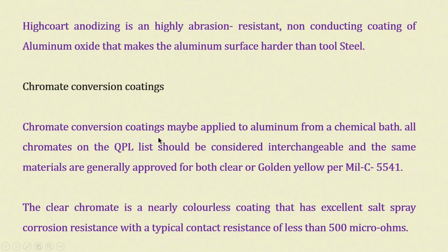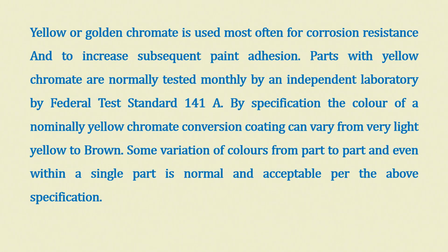Then chromate conversion coatings we had already discussed a little bit, and that also can be applied to aluminum from a chemical bath. All chromates on the QPL list should be considered interchangeable, and the same materials are generally approved for both clear and golden yellow color finish corresponding to the MIL-C-5541 standard. So, clear chromate is also there. It is a nearly colorless coating that has excellent salt spray corrosion resistance, with a typical contact resistance of less than 500 micro ohms. Yellow or golden chromate is most often used for corrosion resistance, and it is used to increase subsequent paint adhesion.